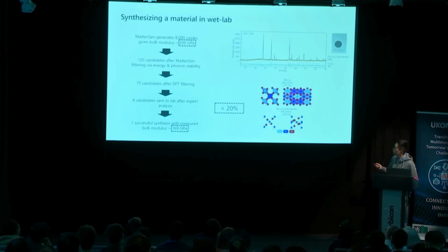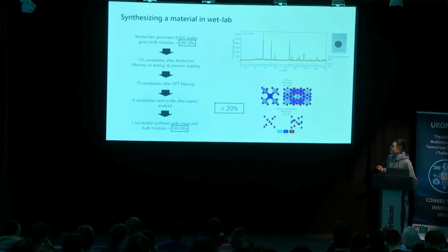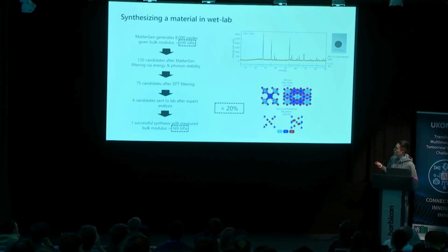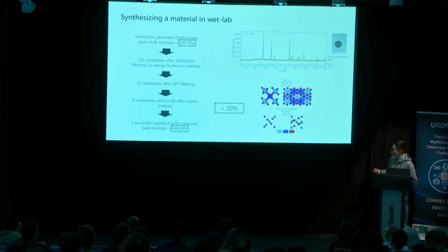So finally, I want to show something in our paper, where we tried a proof of concept. We tried to synthesize one material in the lab to go all the way. In this example, we asked MatterGen to generate materials with a bulk modulus of 200 gigapascal. We generated 8,000 materials, and then it gradually filters down, and we sent 4 into the lab, and one of the syntheses was successful. In the end, the bulk modulus is around 169 gigapascal, which is within 20% error of the conditioned value.